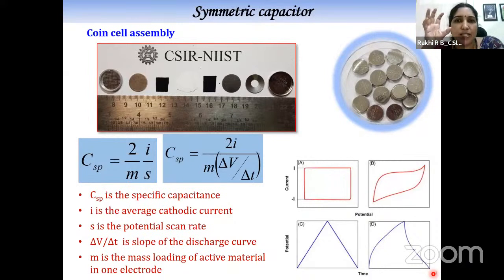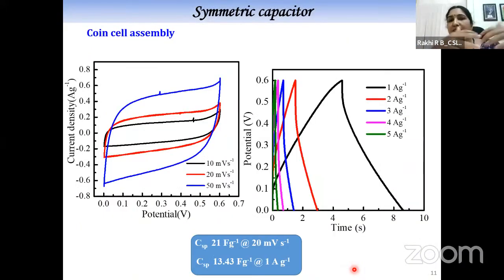Specific capacitance is not the device capacitance. It is actually the capacitance per unit mass of the material, using this formula, where M is the mass of the electrode, I is the average cathodic current in the cyclic voltammetry, and S is the scan rate. But when we report, we have to take the capacitance from the charge discharge measurement using this particular formula, where delta V by delta T is the slope of the discharge curve. Okay, that is the theory.